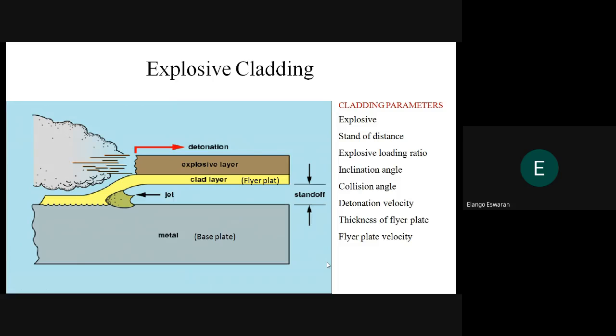When the electrical detonator is detonated, the potential energy stored in the chemical explosive is instantaneously converted into gas, which propagates a shock wave in the flyer plate. This leads to an oblique movement of the flyer plate colliding onto the base plate and the generation of shock compression gas between the plates. During the collision with the base plate, the kinetic energy of the flyer plate is converted into thermal energy. The energy spent at the interface determines the degree of plasticity at the interface and thereby influences the characteristic interfacial undulation. In explosive cladding, the detonation of chemical explosive forces the flyer plate to collide with the base plate to craft a metallurgically strong joint in a very short duration of time.